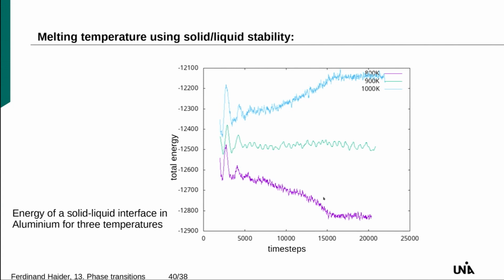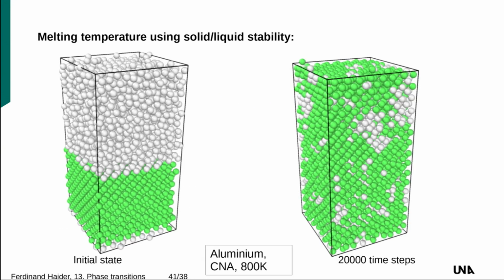I think this is what you already showed - if you go through the temperature you can pinpoint this transition temperature. But what you typically do, what Guru already showed, is that you start with a half molten, half solid system, because you have this metastability in the first order phase transition.